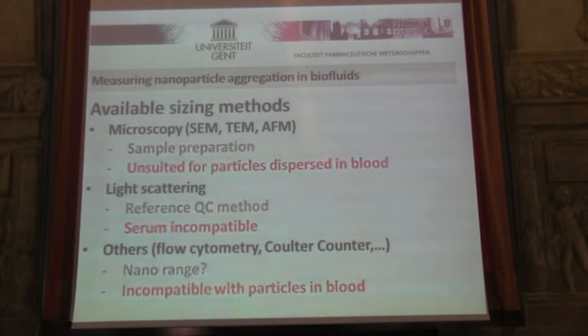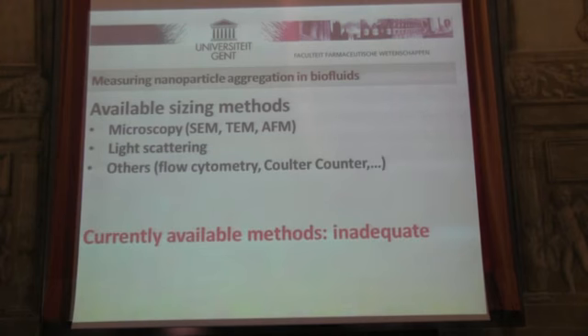So looking at these problems, we realized a few years ago we need something else. We need a new method. And basically independently from that, most of these things happen by coincidence, I'm sure, we were doing single particle tracking microscopy at that time. So what we do is we have fluorescently labeled nanomedicines. Mostly it's the nucleic acids that are labeled with a fluorescent dye. We put them in nanoparticles, and thanks to the fluorescence you can see specific signals of single nanoparticles on this particular microscope in the biological fluid.